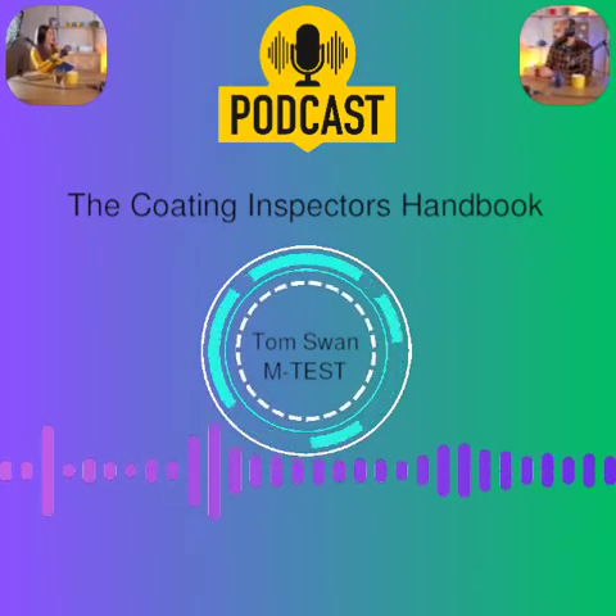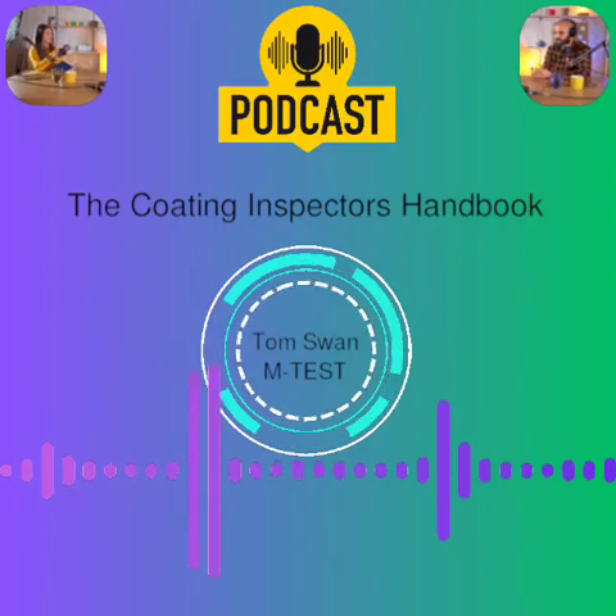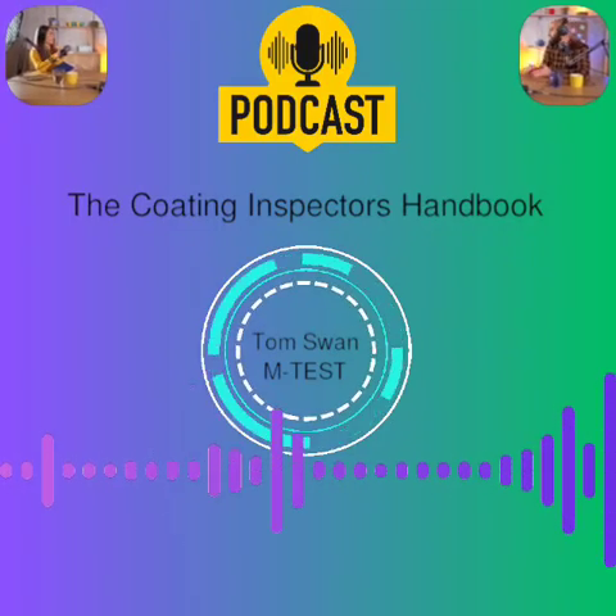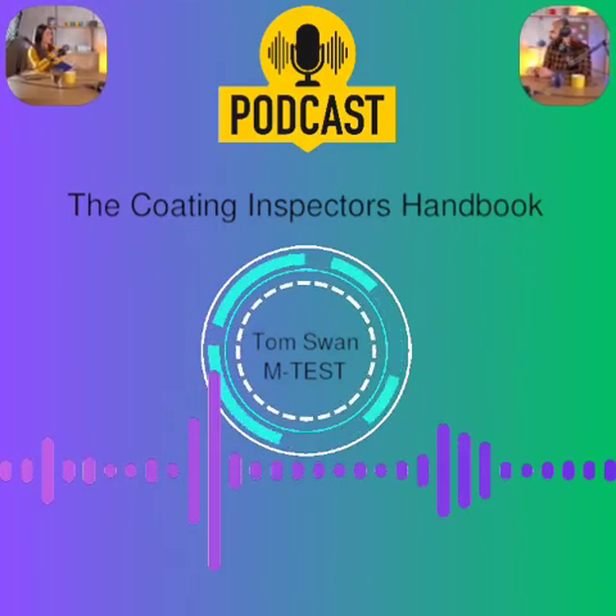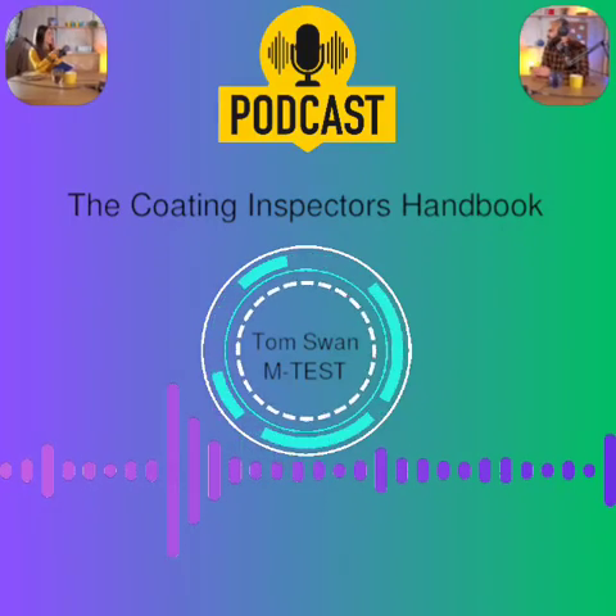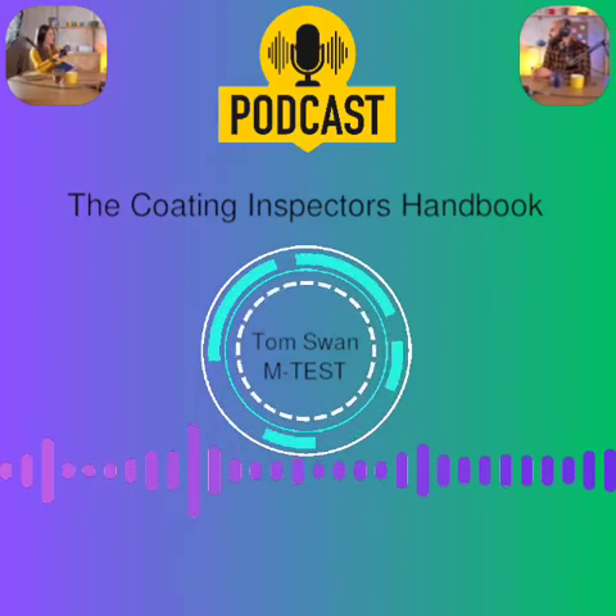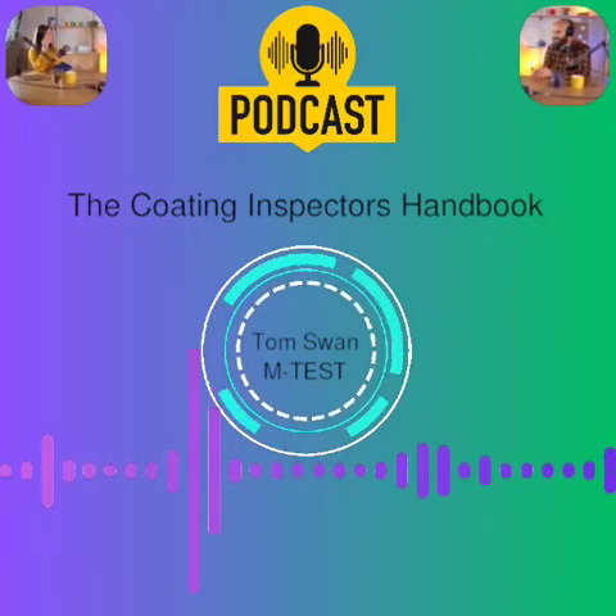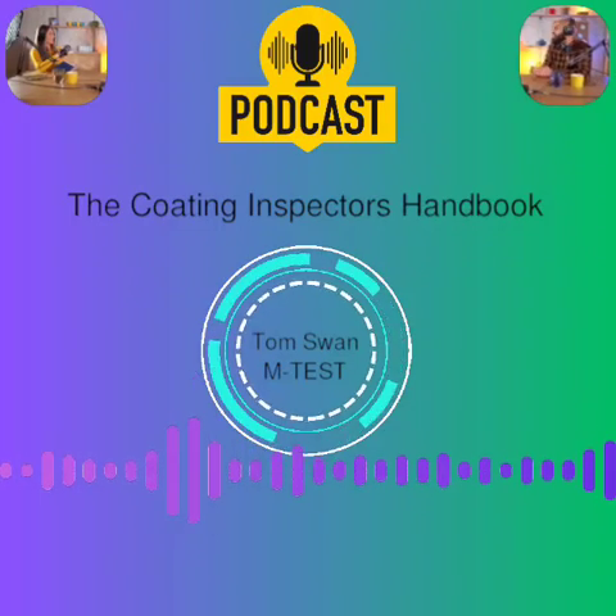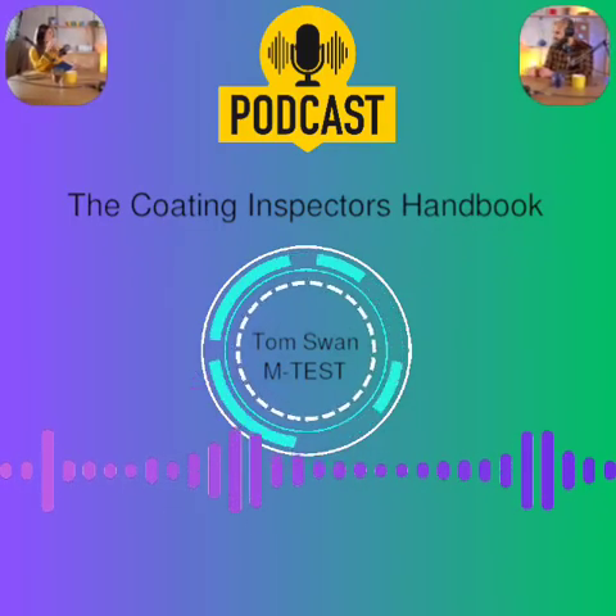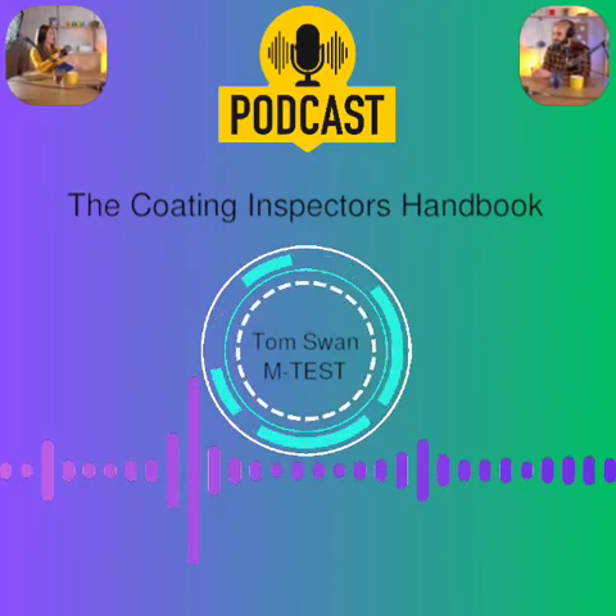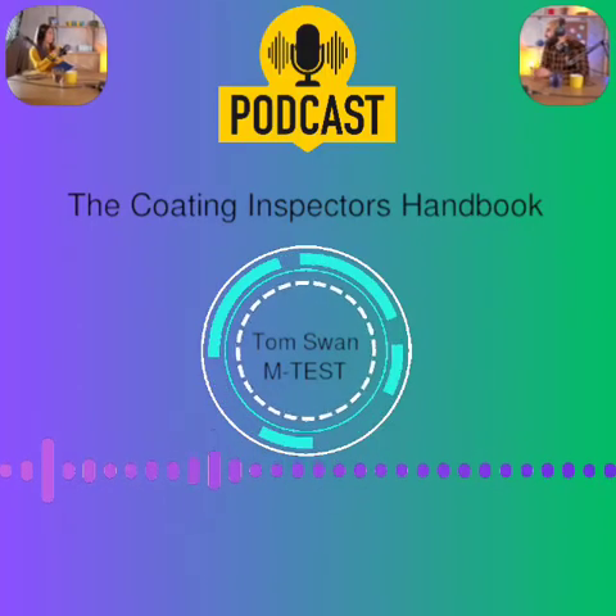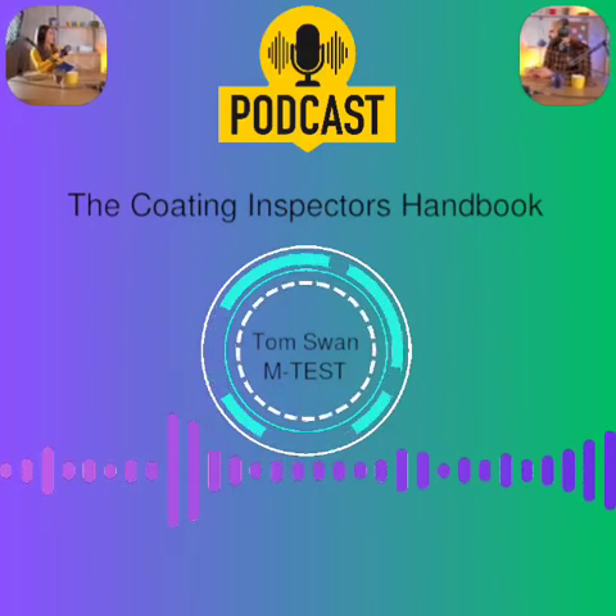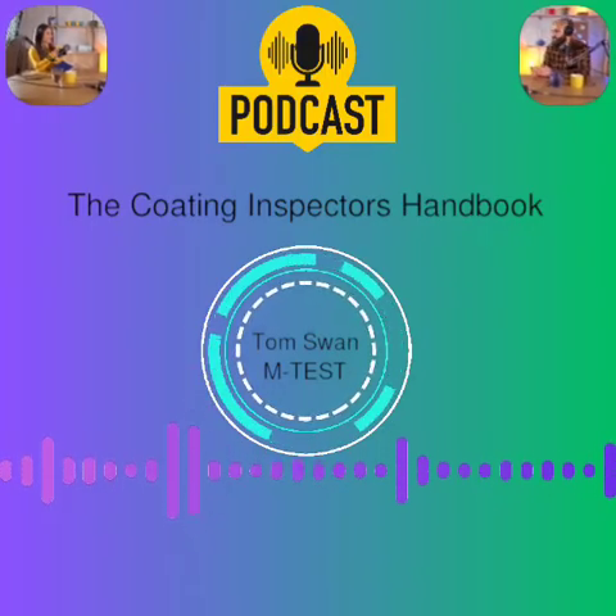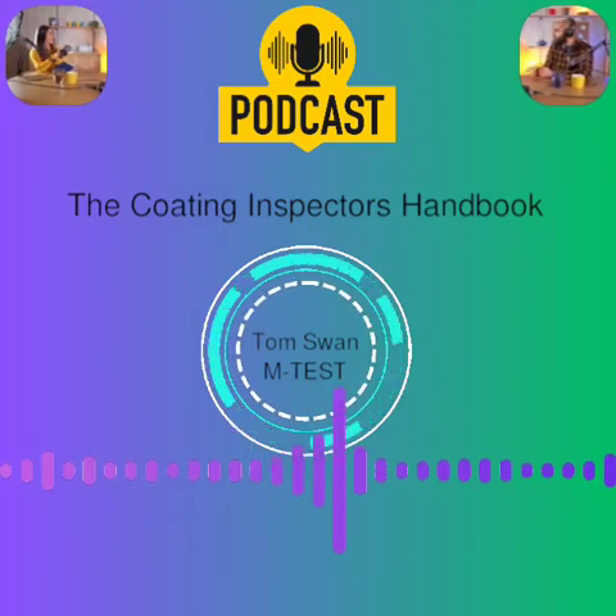How do you use a WFT gauge? The cone type. Yeah, the cone gauge is most common. Little metal or plastic notched gauge. You press it squarely into the wet paint, down to the substrate. Then lift it straight out. Look at the teeth. The WFT is between the highest numbered tooth that has wet paint on it and the next highest tooth that's clean. So if the 4 mil tooth is wet, but the 6 mil tooth is dry, your WFT is between 4 and 6 mils. Any other types? There's the lens gauge for clear coats like varnishes. Uses a lens pressed into the film.